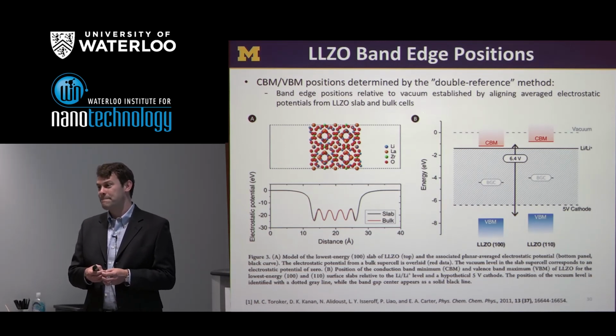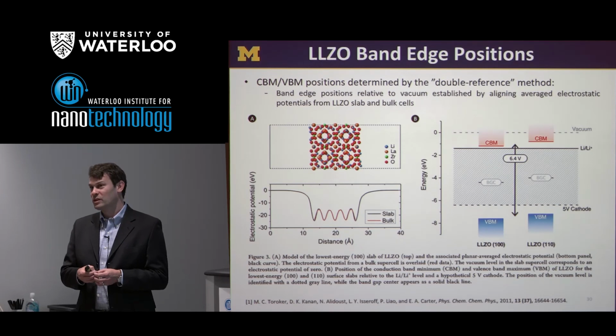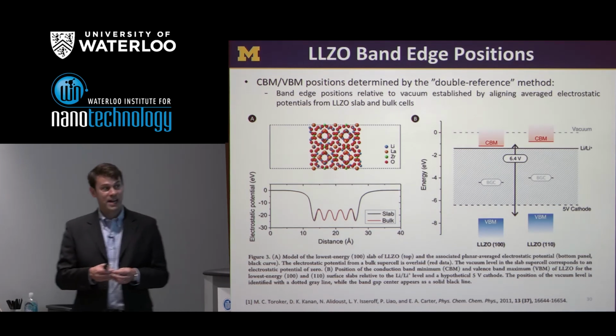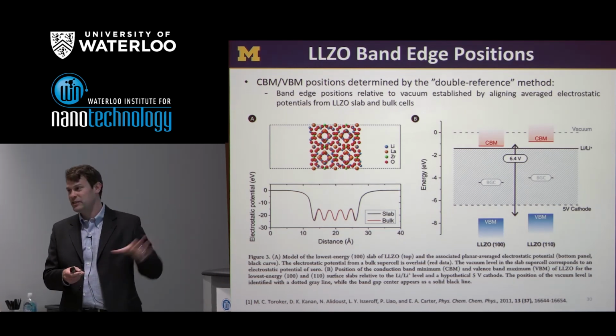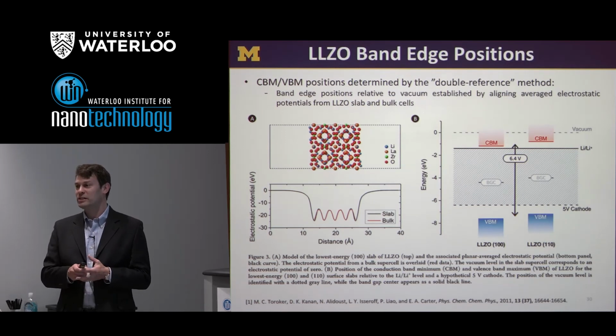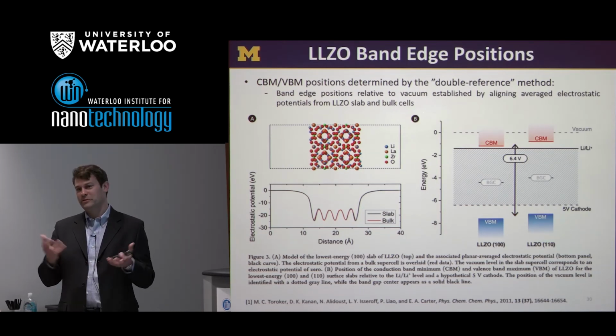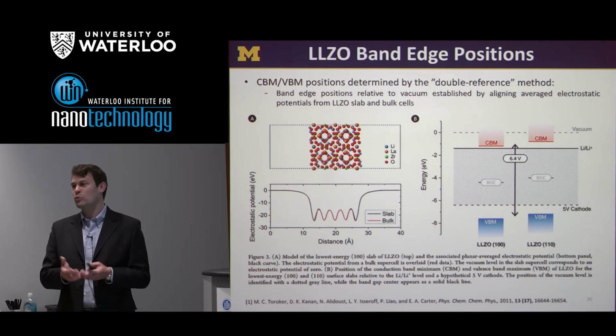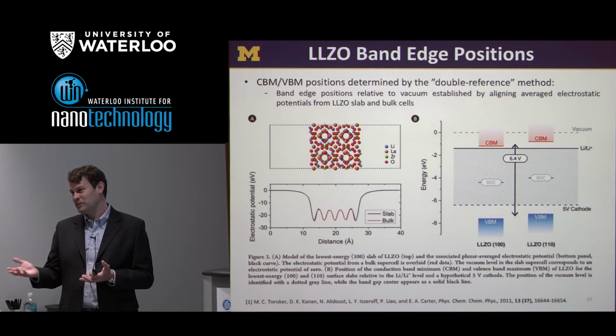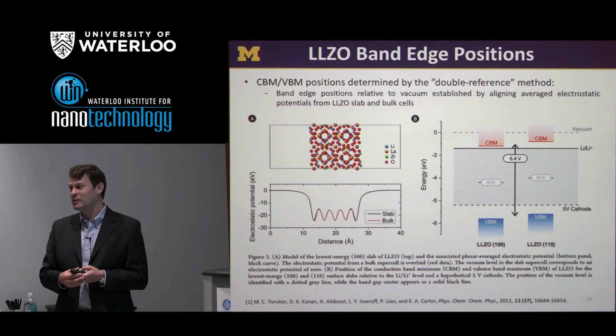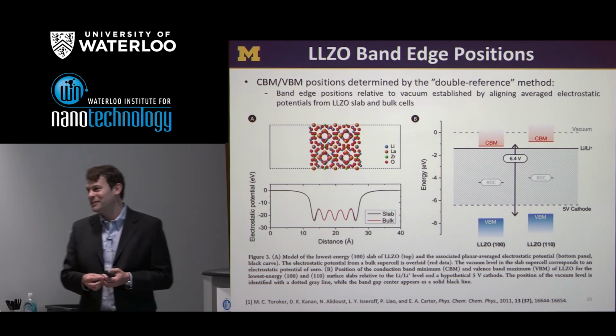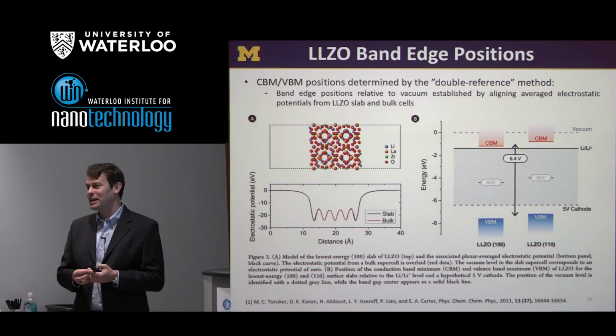But it is quite surface dependent. It will be surface dependent, but honestly, this is such an expensive calculation that we haven't done it for the other surfaces just to see how things change. If you go through, for example, the hundreds of papers on metal work functions, which are easy to calculate, you could see a surface dependence of the HKL index on the work function for those different systems. That would at least verify the general notion I think you're getting at.